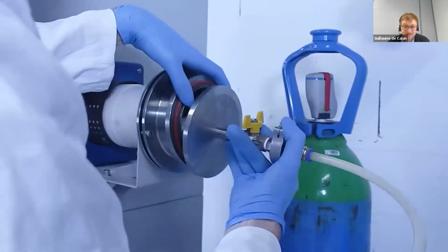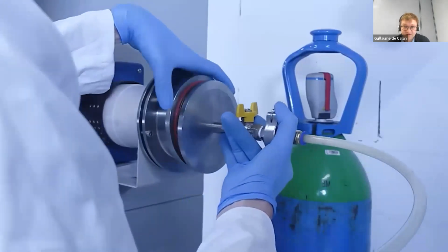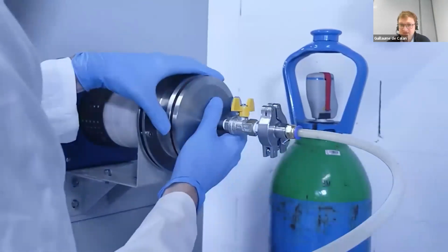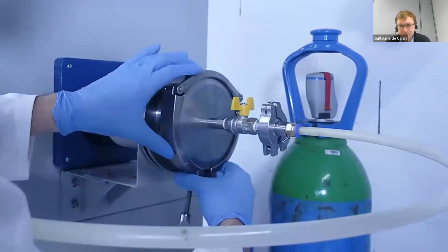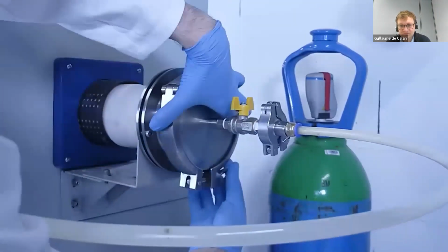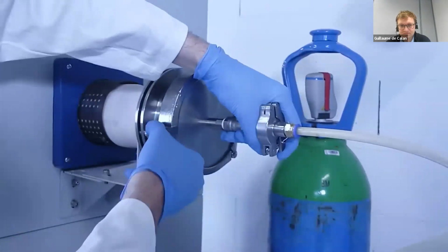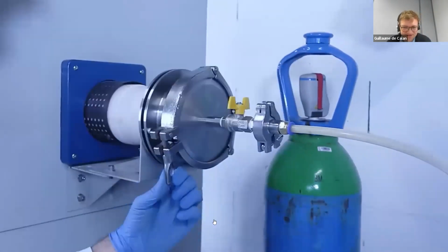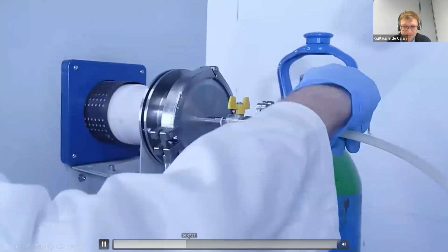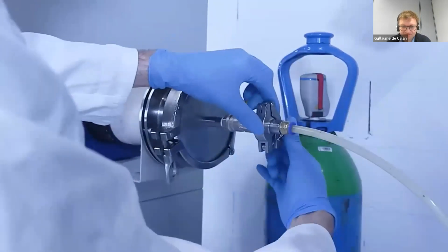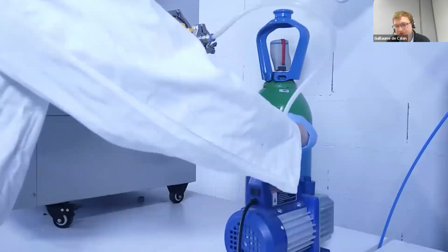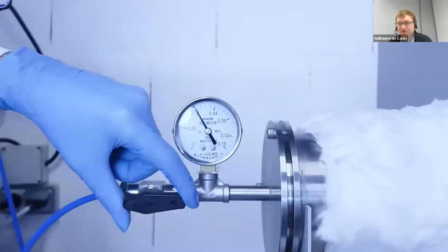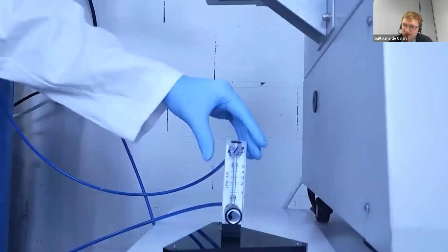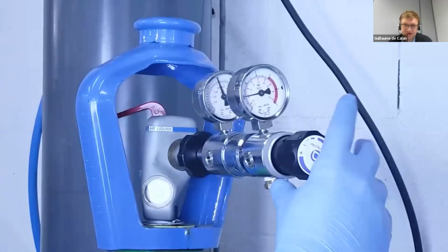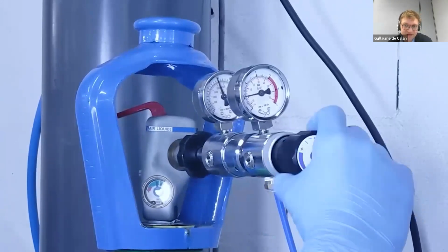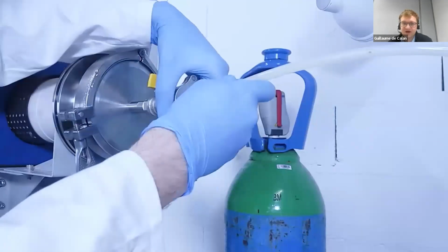So we put the flange that allows to put it under vacuum or under gas. Here you can see we have a vacuum pump. We can use it for flushing the atmosphere at the beginning. Actually, it's optional. We don't always do it because anyway, the process is relatively long and we will flush the furnace during the process. You open your gas supply, which is usually hydrogenated argon. We put a slight overpressure of 0.2 bars.